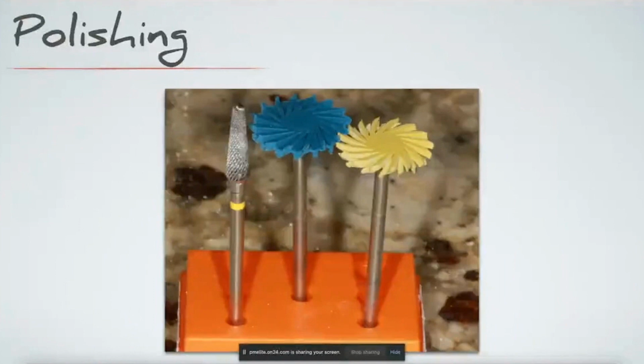So here's my entire armamentarium for finishing a zirconia restoration. Literally 3 burrs, right? If you want to call the 2 on the right burrs. One fine acrylic burr to remove the sprue, the blue Meisinger twist wheel in the lab handpiece to remove the scratches, and then the yellow one to polish and get the occlusals really nice and shiny before delivery.